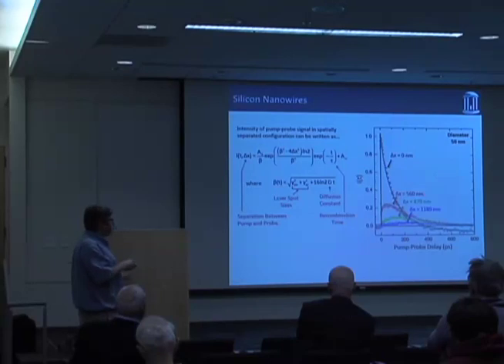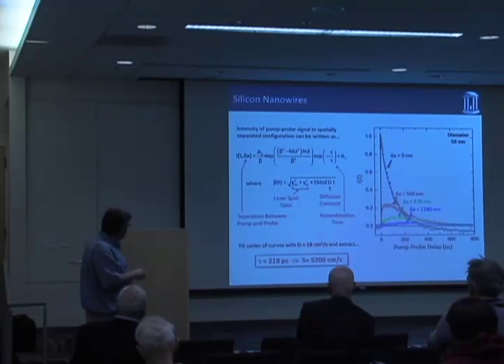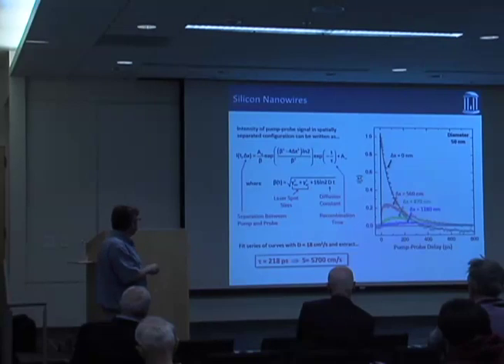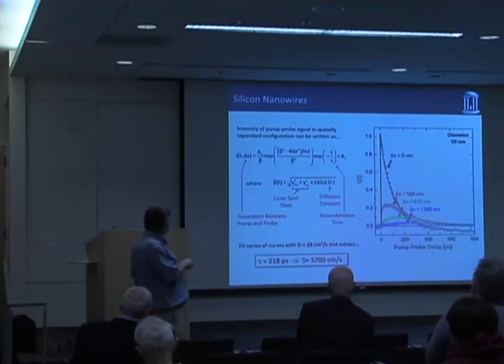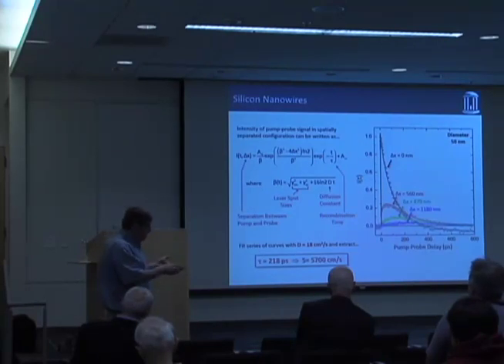So even though every individual transient is highly non-exponential, the population decay is described by a single time constant. And that time constant in this particular case is around 220 picoseconds. If I use that equation that I talked about earlier relating lifetime to surface recombination velocity, I can pull out a surface recombination velocity of about 5,700 centimeters per second. And all this was fit with the bulk diffusion constant. So we don't have to take transients at all these different spatial locations. I can get the lifetime simply by measuring the decay in the spatially overlapped configuration. Then I can do this all day long, or my students can do it all day long.